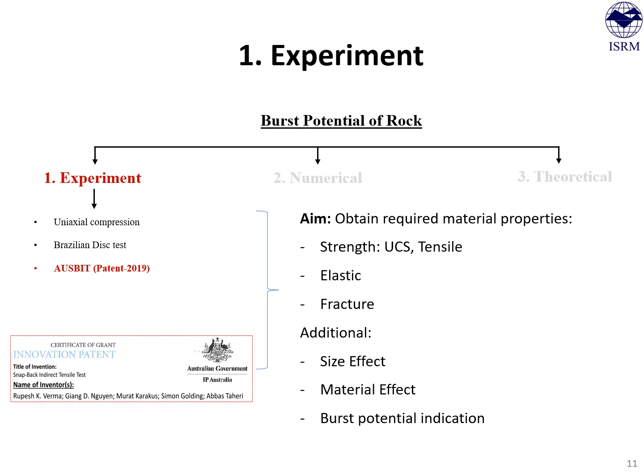Poisson's ratio. When we started doing the Brazilian disc test, we realized there are two key issues associated with this experimentation. The first one is its reliability. In the literature, we found that the reliability of these results heavily depends on the crack initiation point when the disk specimen is compressed diametrically. And the second issue we found is the uncontrolled cracking of the disk specimen, which is the result of local scale uncontrolled dynamics, which has not been addressed in the available literature efficiently.